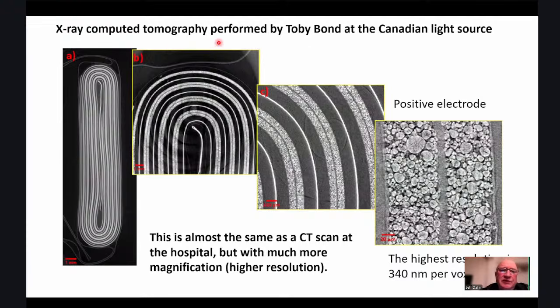So we wanted to see what was happening inside these cells. So we did X-ray computed tomography of them at the Canadian Light Source with Toby Bond doing the measurements. And what you can see is the pouch cell, and then a zoom in, and more of a zoom in. And in this panel C, I'll describe what you see. This very bright line is the copper current collector and the negative electrode, and then the graphite layers on either side. And then you see the positive electrode with an aluminum foil current collector down the middle. And if you zoom in even more, you can see the NMC particles in the positive electrode. And what has happened to these NMC particles over this long charge-discharge cycling?